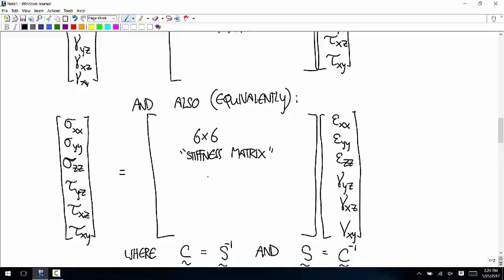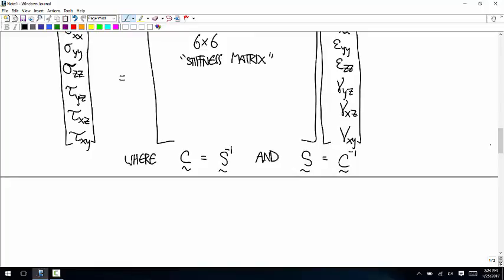And if we know the stress, we can calculate the strain. That's the same thing we know with springs. Once you measure the spring constant, if you see that the spring is compressed a centimeter, you can calculate the force. That's a lot of calculating power we have. The problem we still have is, in order to represent a material, we need to find these 36 elements of the stiffness or the compliance matrix.